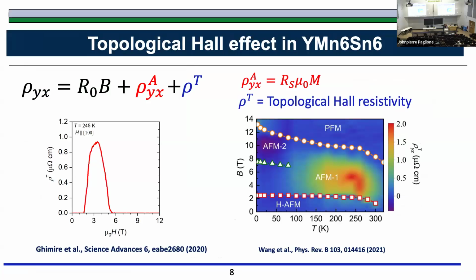If you measure the Hall effect, then you get it from the electron count. Every conductor has this normal Hall part. Then if it has magnetism, especially ferromagnetism, or now these days even antiferromagnetism, you can get the anomalous term, which comes from the band structure part. But there was some additional signal, and some other group also reported this during the same time, and they did a little better job because they mapped out the whole phase by doing very, very detailed calculation. It was appearing only at a certain range of temperature, and especially the interesting thing was at high temperature, whereas the magnetic structure was the same from 1.8 Kelvin all the way to 300 Kelvin.